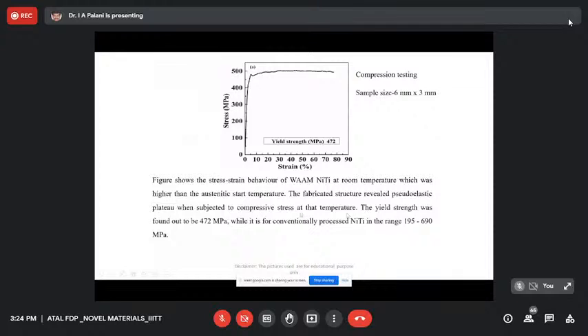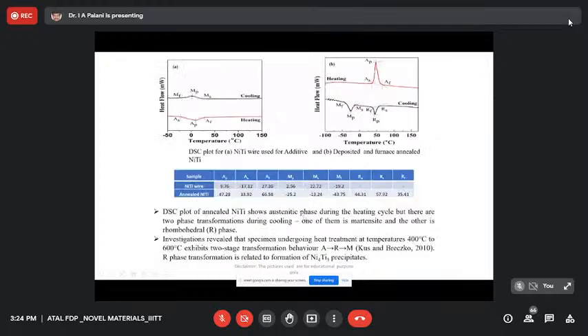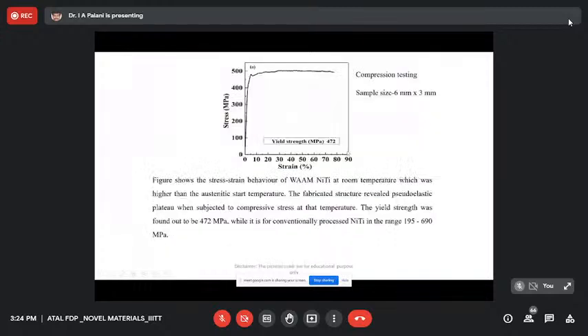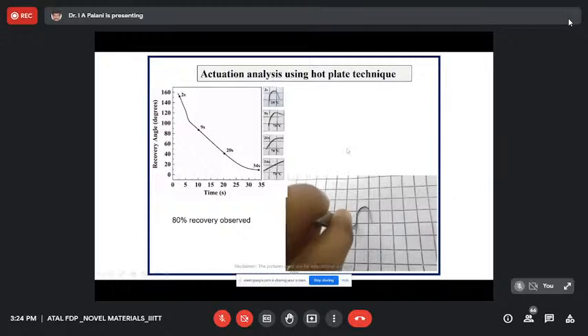Okay, so we did a DSC analysis as well as an XRD analysis. With respect to XRD analysis, we were trying to investigate the austenite phase and the martensite phase. And with respect to DSC analysis, we could narrow down our austenite start, austenite finish, and the martensite start and martensite finish temperatures. We also had a certain amount of R phase, a rhombohedral phase, which was observed in the system, and this is a kind of mechanical testing which we have done on it.